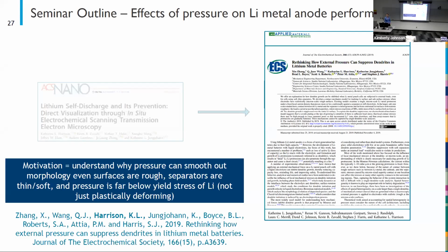So we were motivated to understand why pressure actually matters. I was talking to one of my colleagues, Steve Harris at Lawrence Berkeley National Lab, and he posed the question, why does pressure really help when real surfaces are rough? You've got this big pressure distribution. The separator's really soft. Aren't you just going to be squishing the separator? And then we're really operating at pressures that are generally considered to be lower than the yield stress of lithium. So we aren't plastically deforming the lithium. It has to do with something else.